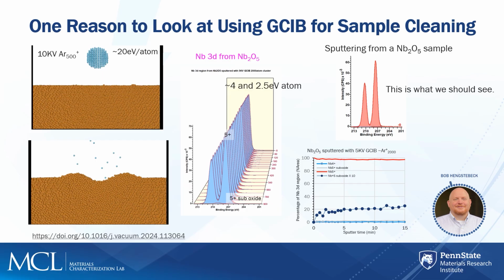But what would happen if we go back to that same Nb2O5 and sputter for a long time? Well, as it is, we're not seeing any +4, +3 generation. There is a very small amount of subsurface oxide that's still being formed, and again, that was showing in that damage layer of probably less than a nanometer. It's showing up as a little tiny shoulder to the right of the niobium +5, if you look at it there. And to give you an idea what that looks like in terms of percentages, I actually had to multiply that by 10 to be able to show the graph that you're looking at on the right.